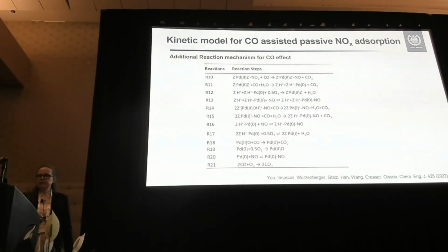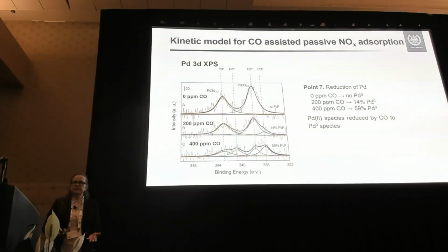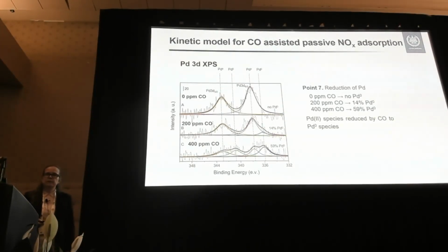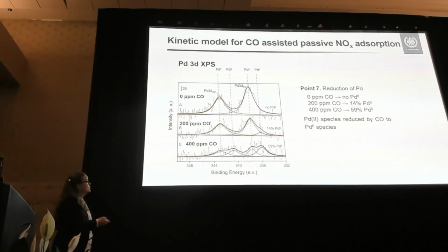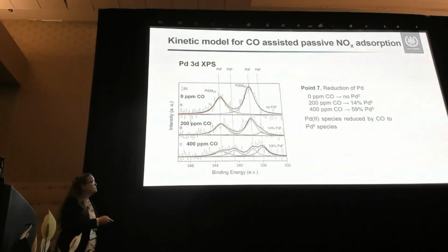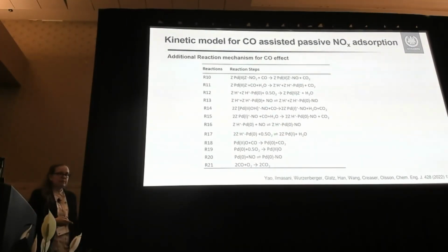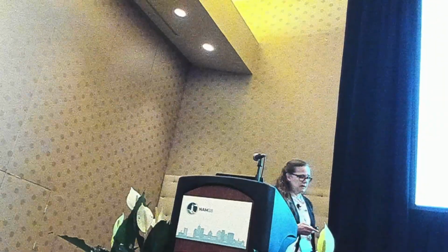So we suggest in the modeling that the main reason for the enhancement of NOx adsorption activity with CO is due to changing the oxidation state. So then we add in reaction steps: reduce the palladium oxide by CO, and also the palladium that's charged is reduced. And we have also reduced the palladium oxide particles.